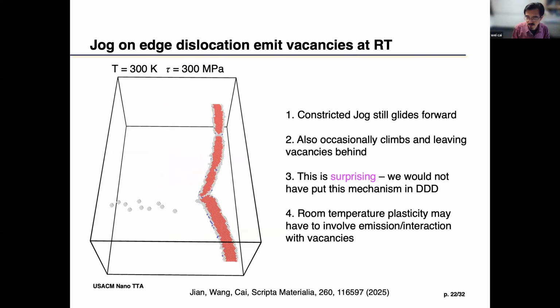And that unfortunately also means that initially what I thought was a much simpler problem, where you can focus on FCC because then you just have dislocations interacting with each other to explain the stress strain curve, right? But now it seems like the dislocations, while they intersect with each other, will have jogs. That's unavoidable. But then the jogs will spontaneously want to climb and then emit vacancies. So you can imagine all of these vacancies are there, and then the next dislocations come in, they will interact with these vacancies, right? So it's quite a complicated scenario.